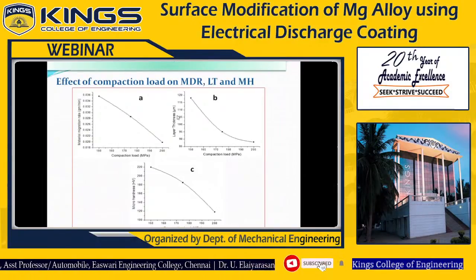Effect of compaction load on MDR, layer thickness and micro hardness. MDR means material deposition rate: how much material is eroded from the electrode and deposited over the surface, which is assessed by the MDR. Here, as you can see with the cursor movement, at the lowest compaction load the material deposition rate is very high. Further increasing the compaction load, the material deposition rate drastically decreases, because at low compaction load the density of the prepared electrode is very low. So when the current is supplied, it erodes a high quantity of material from the electrode and deposits it on the workpiece. Further increasing the compaction load, the density of the electrode drastically increases. So with a higher density electrode, the material deposition rate is very low.